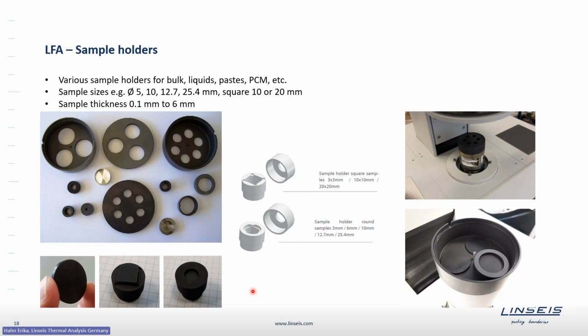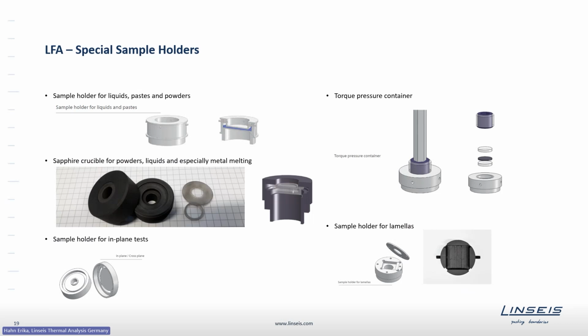As just said, the basic idea of the laser flash is to measure solid samples, but that can be extended to further applications. On this slide you see some of our special sample holders. For example, we have sample holders for liquids, pastes, and powders, where we have a closed bottom and top. Important here is that the lid is fixed to the bottom of the sample crucible. In the middle, we have a precisely defined thickness, which won't change during the temperature measurement as the lid is fixed. For the case that, for example, a liquid expands at higher temperatures, we have some excess volume on the sides where the liquid can expand without spilling out of the sample holder.